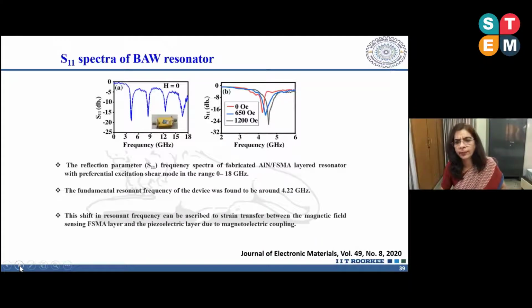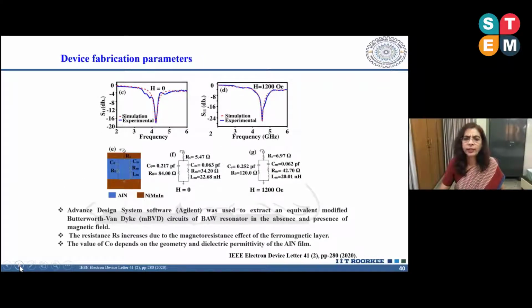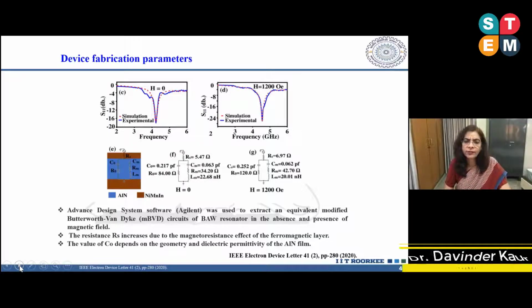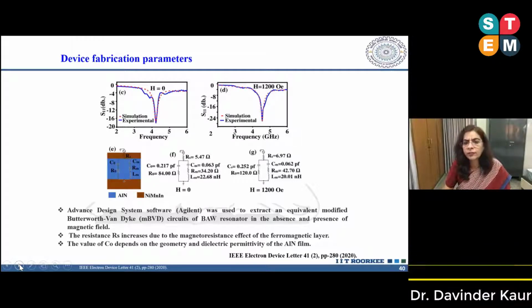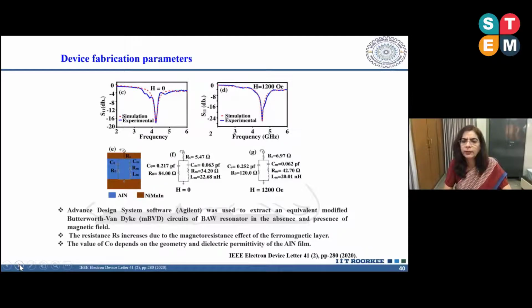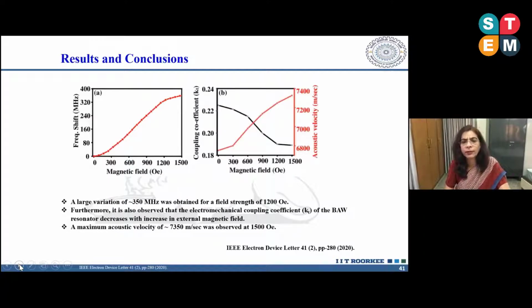Next please. So then we also tried to do some software modeling in this work, and the Advanced Design System software was used to extract the parameters R, C, RM, and LM at zero magnetic field and at 1200 Oersted magnetic field. This is the experimental curve and calculated values from this software, and they match quite well.